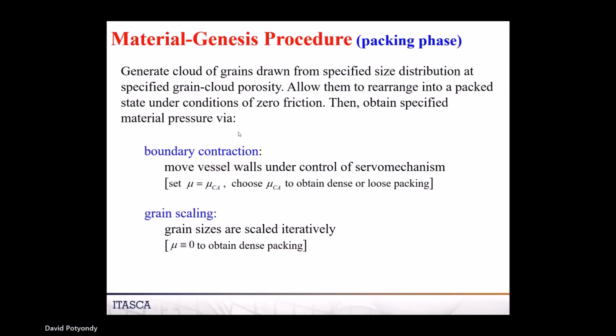Then there's a control here. You're saying, but what's the final pressure you want for this to be? So there's two ways to do it. You can basically contract the boundary, okay? And if you're doing boundary contraction, that's where you're going to squeeze the walls in or out, okay? You're going to set the friction coefficient of the material to this. The friction during, that means the friction coefficient during confinement application. And we talked about this. While you're squeezing it, if the friction coefficient is high, it'll pack to a system that's not quite as dense. If the friction coefficient during that is low, it'll pack to a denser system. Okay, so that's boundary contraction.